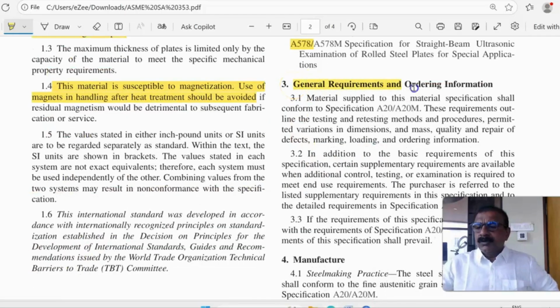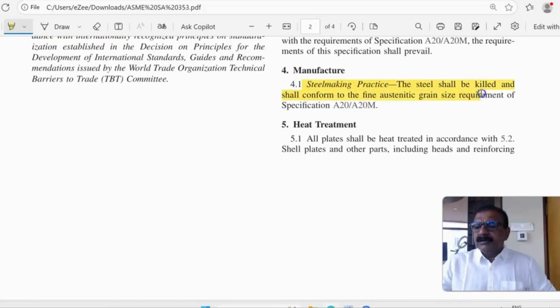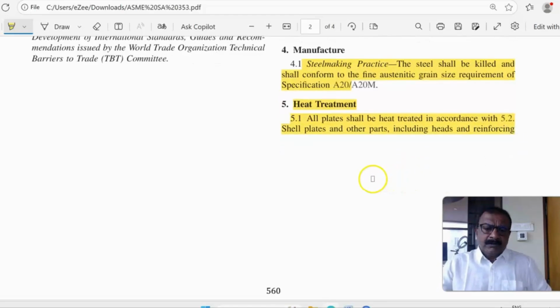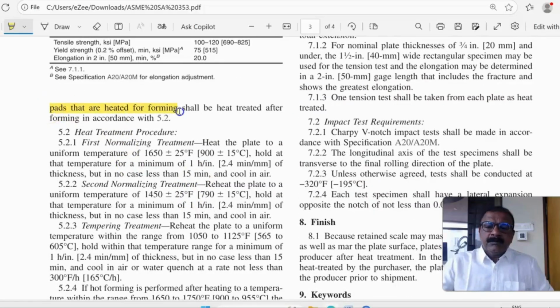Then general requirements, ordering information and supplementary requirements are given in A20. Supplementary requirements are given at the end of this specification. We'll see that also. Then steel making practice. The steel shall be killed and shall conform to the fine austenitic grain size requirement of the specification given in A20. Now heat treatment: these plates shall be heat treated in accordance with 5.2, and also shell plates and other parts including heads, that is dish ends, and reinforcing pads, all these are to be heat treated after forming as per this 5.2. We'll see the 5.2 here.